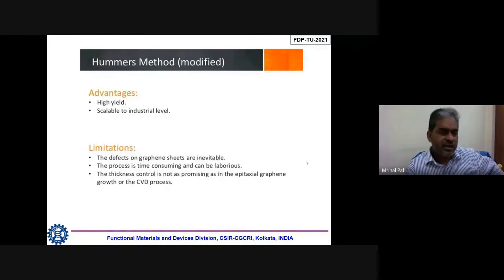So it has some advantages and disadvantages. It is possible to make a high amount of 2D material using this chemical process, and it is scalable, so this process can be used on an industrial scale also. The limitation is that it is not perfect graphene or a perfect 2D material. Some defects will always be there, and it is also difficult to make a single layer, so it will be a few-layer thick 2D material. These are the limitations of this process.